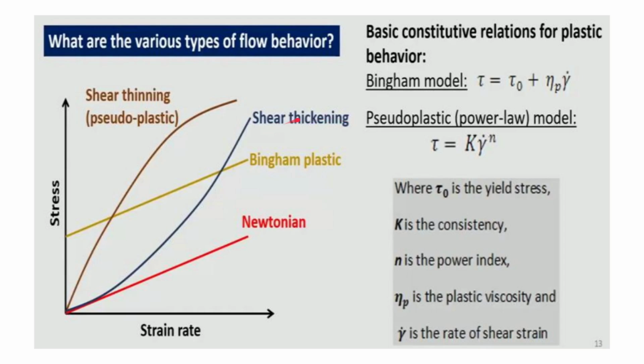In the case of shear thickening, with the increase of strain rate, the amount of stress required also increases. So that's why it thickens. More capacity is required. For basic constitutive relations for plastic behavior, these four types of stress strain rate behavior are obtained for flow. The Bingham model can be written as tau equal to tau naught plus eta p gamma dot. For the pseudoplastic power law model, that is shear thinning, tau is equal to k gamma dot to the power n, where tau naught is the initial yield stress, k is the consistency, n is the power index, eta p is the plastic viscosity, and gamma dot is the rate of shear strain.